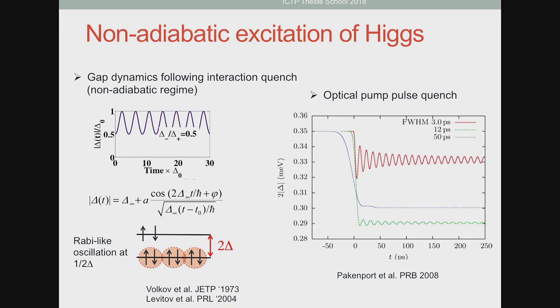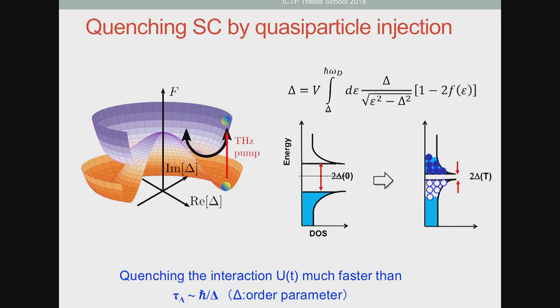And what you see is that for sufficiently short pulses, in that case 3 picoseconds, you have oscillations. But if you take a very long pulse, so if you don't satisfy the non-adiabatic condition, which would be to have a pulse whose duration is shorter than the inverse of 2 delta, essentially, you see nothing. So how to do that?